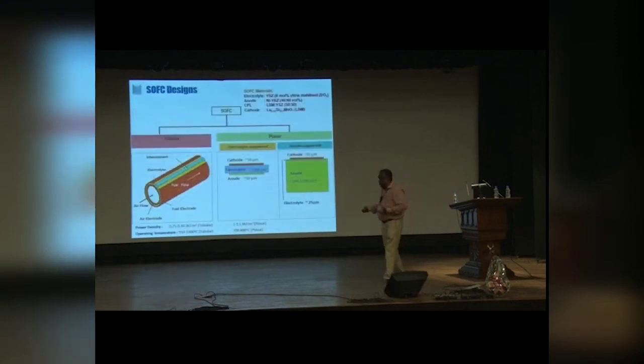So now I am coming to the structures. As you can see, they are a tubular structure. It was by Siemens Westinghouse, started 3 decades back, but they could not market it because of the high cost. But these are basically the simple ones, and in the mid 90s, people started using anode supported solid oxide fuel cells. In the anode, basically nickel oxide, and on top of that you have the electrolyte, which is about 25 micron, a very thin electrolyte, and then you have the cathode. So cathode and anode are porous, and you have the electrolyte. So you have here anode, electrolyte and cathode.